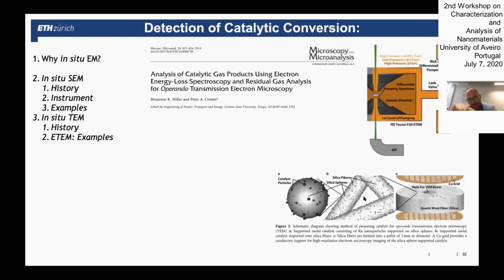And then they pressed a pellet and made a central hole so that the electron beam can, at least at some place here, still penetrate through. So there's a lot of catalyst, and there's one place where the beam can go all the way through because the beam in a transmission electron microscope needs to go through. So they have this hole here, and they packed this whole pellet between two TEM grids and put that into the chamber.